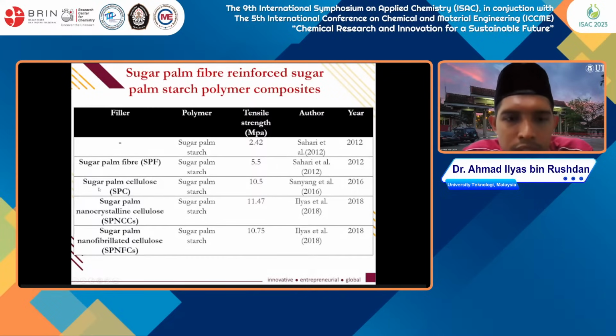For example, sugar palm cellulose reinforced with sugar palm starch increased up to 10.5 MPa, with this study using 30% loading. In 2018, using only 0.5 weight loading gave much better results compared to the cellulose loading, due to the size of the fiber that affects the interaction of the fiber with the starch.